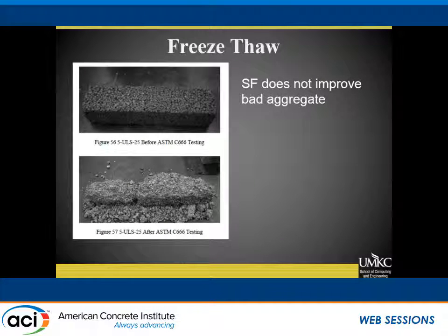So Freeze-Thaw, we ran Freeze-Thaw on the fixed void samples, and turned out we had some limestone that wasn't particularly durable, and we had some river gravel that wasn't particularly durable. And so all I can say is, if you had bad aggregate, the silica fume didn't help. There was no difference. It just had poor performance all over the board. So there are no conclusions on that side of the Freeze-Thaw testing.